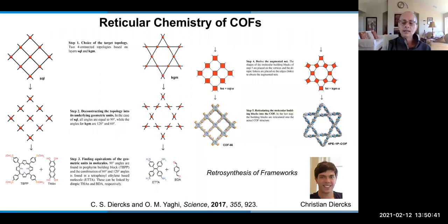So the way this framework chemistry works is we call it retrosynthesis of frameworks. You imagine which network you want to make, dissect it into its building units, look at the building units' geometric requirements. In this case, the units require 90 degrees. Well, we can then pick the molecules that provide you with that and the linkers. And in this case, 120 degrees and 60 degrees, and you can identify the organic molecules that provide you with those angles. You put them together, simulate the X-ray powder diffraction, then go to the lab and make them.